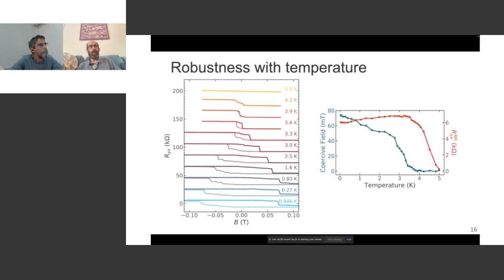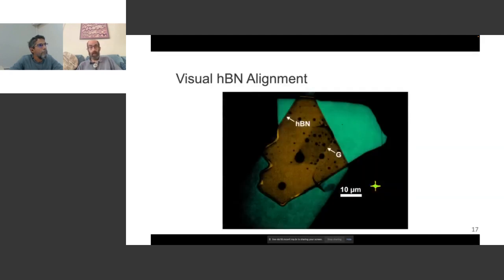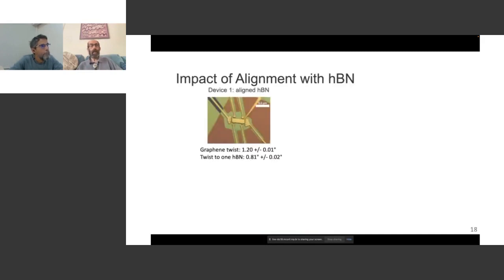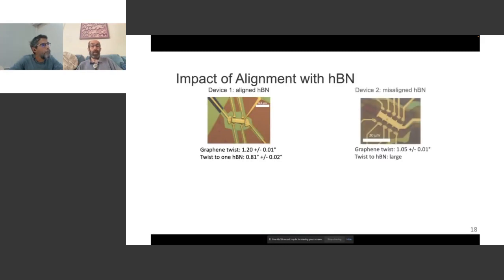And in terms of why we saw something that was so different from what had been seen before in this system, it turns out that there was something that we had done unintentionally. So when Aaron looked back at the pictures he had taken while making the sample, he noticed that an edge of the graphene was parallel to an edge of the boron nitride, the insulating layer that was used to encapsulate it, to protect it from the outside world. And so this turns out to have an impact.